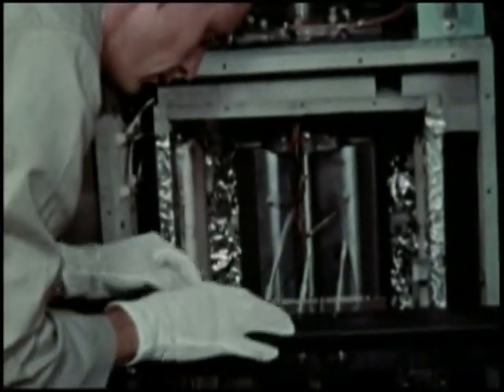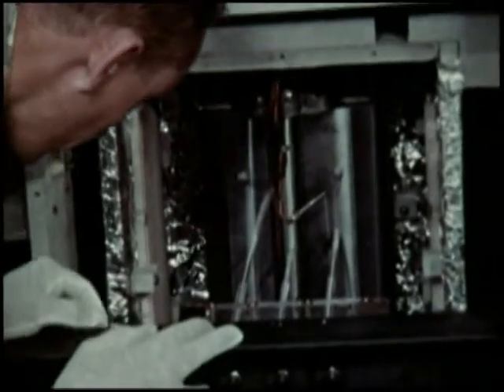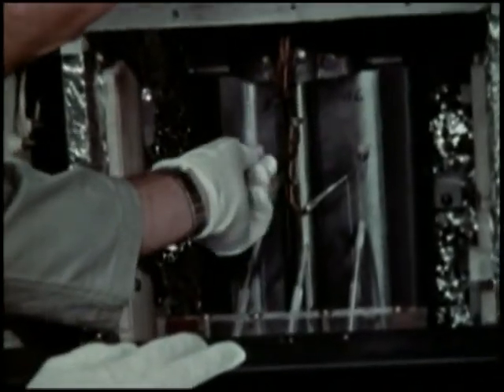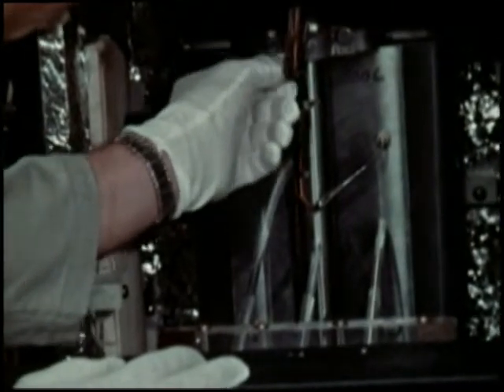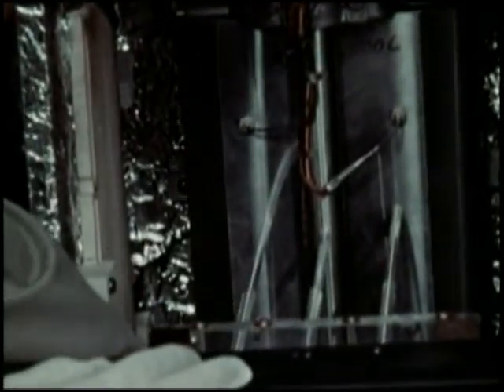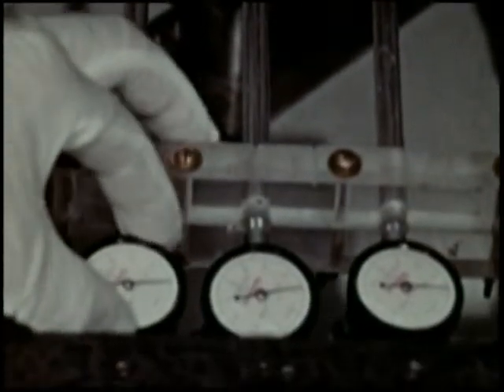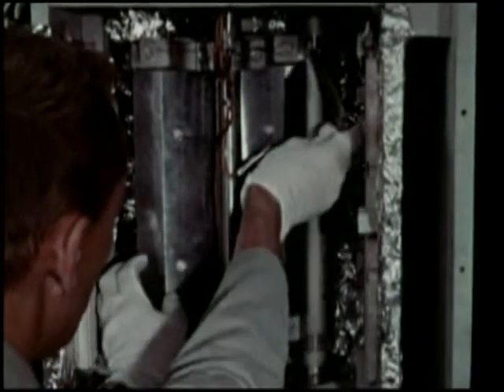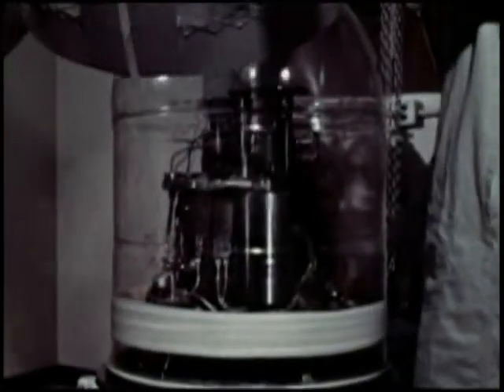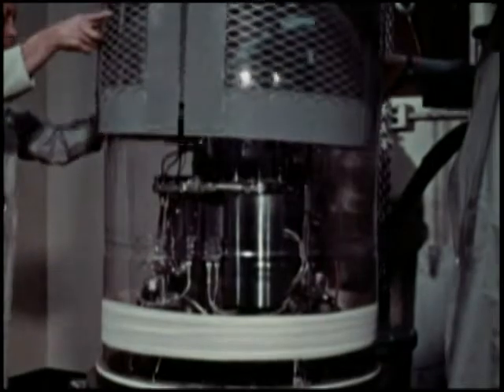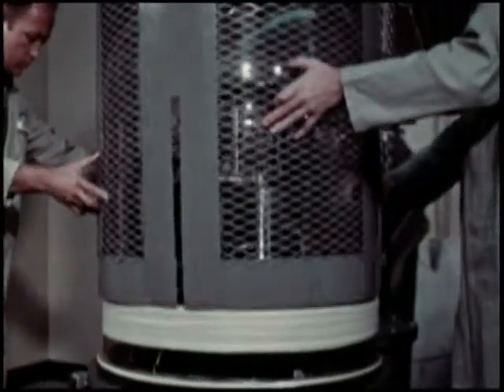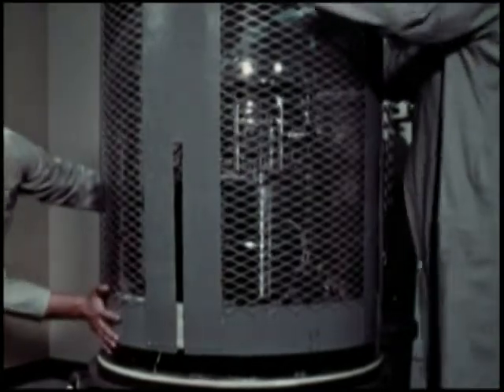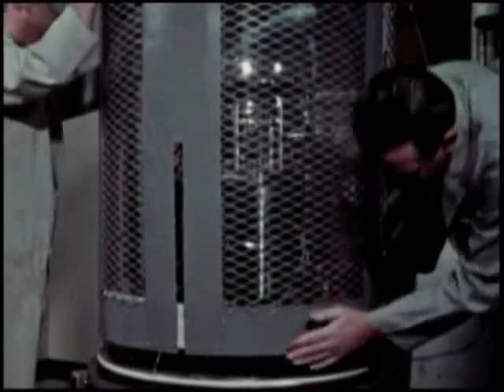Not only must reactor components be designed for full lifetime operation in space, but they must be capable of performing at ground test conditions. Oxidation of beryllium components, such as the reflectors shown here under test, is a problem during ground testing where moisture and oxygen are present. Catastrophic failure has been observed within hours when unprotected beryllium has been tested at SNAP-8 operating temperatures in laboratory air. Protective coatings are under development. To date, an anodized coating appears to hold promise as an interim solution. The ultimate answer to this oxidation problem is to eliminate it by conducting ground tests in ultra-high vacuum environments.